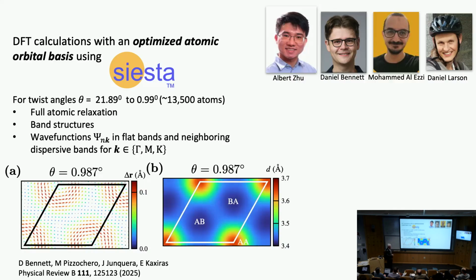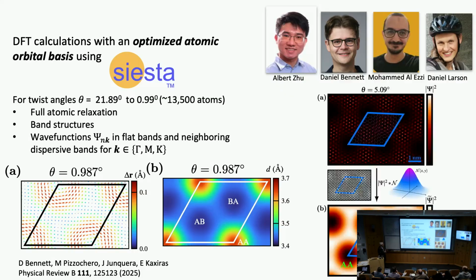First of all, the atomic relaxation. We went through that. It's exactly the same. So this is now atomic relaxation without any tricks about configuration space, generalized stacking fault energy landscapes, and so on. This is straightforward minimization of the energy in large unit cells. The calculations agree exactly with the earlier predictions that I already mentioned. And I'll focus now on some features of the electronic states themselves, which are shown here schematically, so that you can be oriented about what the pictures mean.